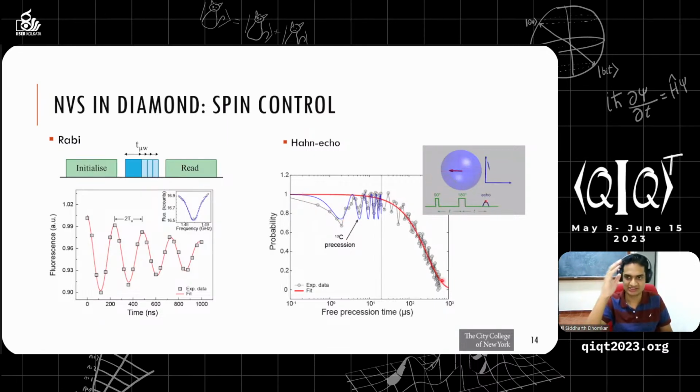And then you can extract that phase later on by again bringing that spin state back onto the z-axis. I'm assuming that at least some of you know the Bloch sphere. So you start in spin 0 state, then you can create a superposition state, which then evolves in the presence of this AC magnetic field. The phase gets encoded, and then at the end you can extract that phase. So you can use this even to do AC magnetic field sensing.